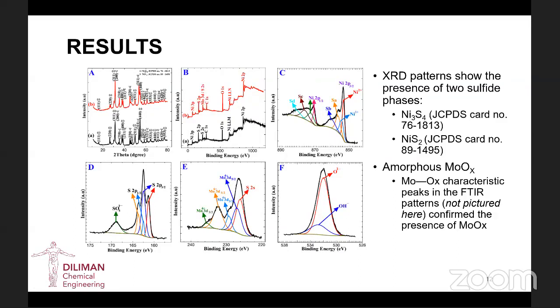And we also have the XRD patterns, which show the presence of two sulfide phases. Although the image is a little bit small, you can see the image in A shows peaks corresponding to the two nickel sulfide phases listed here, and the presence of molybdenum oxide cannot be seen on the XRD because it is amorphous. If we have an amorphous substance, then usually you can just see a very broad peak or no peak at all in the XRD.